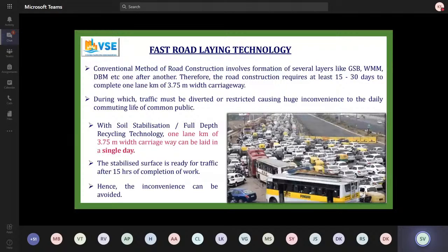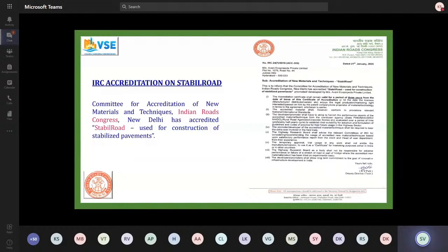Once we stabilize it, if there's an emergency, we can allow traffic within 6 to 7 hours, but ideally we would like anywhere between 12 to 15 hours. So there's no issue with allowing traffic, whether it's a rural road or there's a lot of traffic in the city. We can allow traffic within 6 to 7 hours. StabilRoad has been accredited by the Indian Roads Congress, and like I said, we've been using it for more than 3 years.